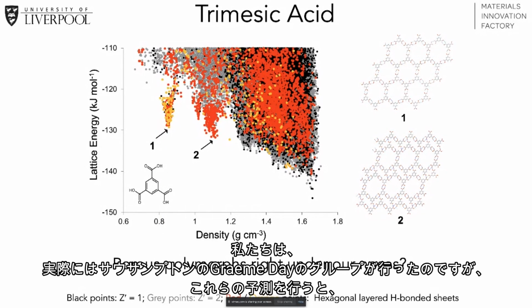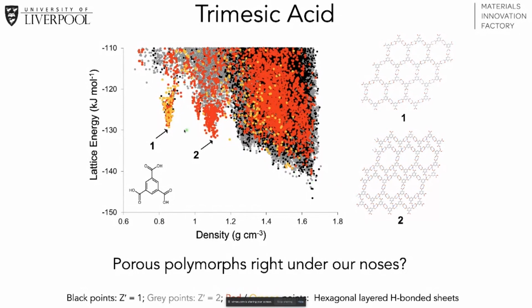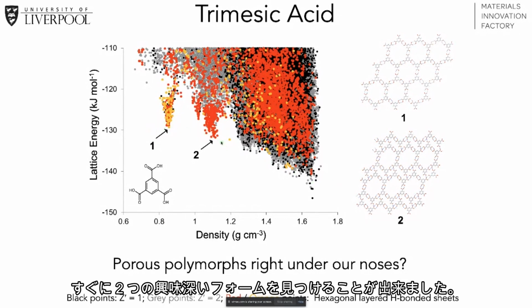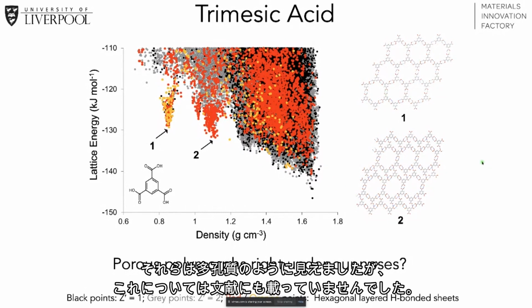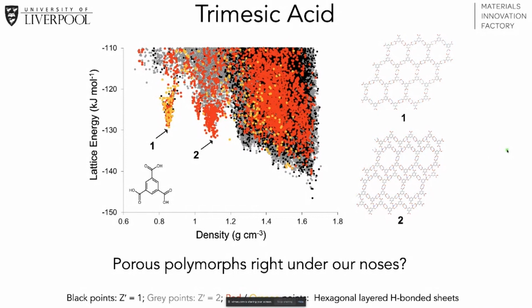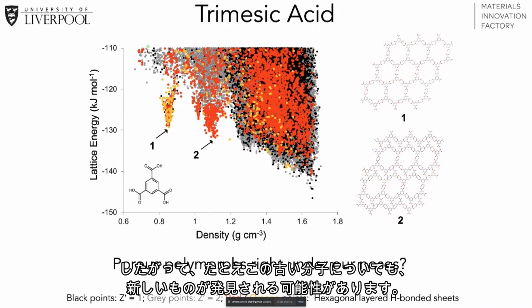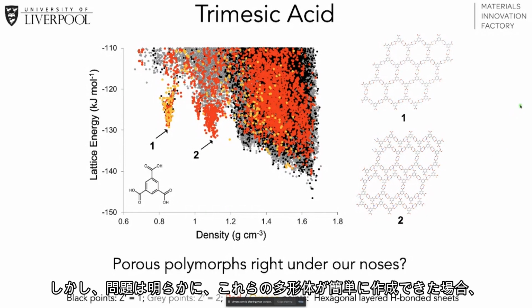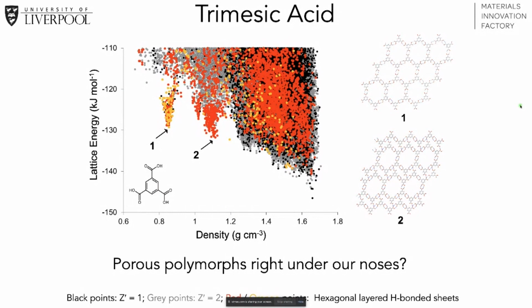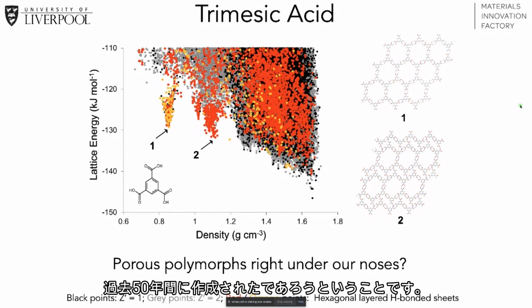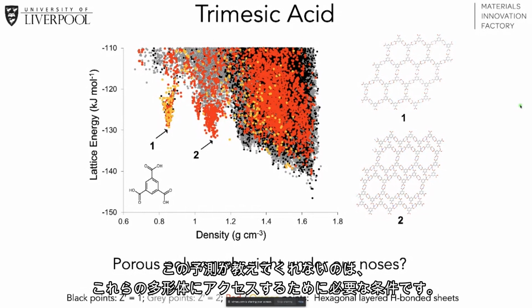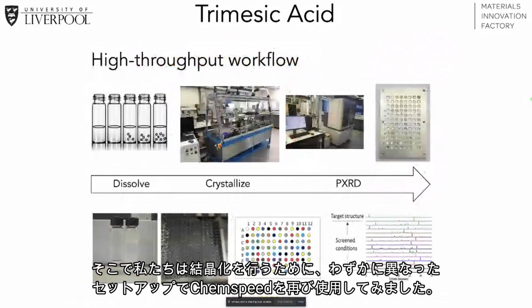So Graeme Day's group in Southampton did these predictions, and immediately it looks like there are two forms here that look interesting. They look like they should be porous, and they weren't in the literature. So even for this old molecule, we get a suggestion that new things might be discoverable. But the problem is, obviously, if these polymorphs were easy to make, then they would have been made in the last 50 years. So what these predictions don't tell you is what conditions you need to use to access these polymorphs. So what we did is, again, use the Chemspeed platform, slightly different setup, but to do crystallization.